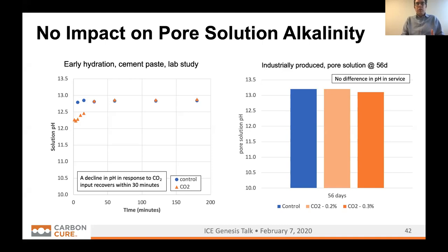Ultimately, a big question when you say CO2 plus concrete is, well, now you're carbonating the concrete. That's not a term we would use. We would say it's CO2 utilization for concrete production. Concrete carbonation refers to, in general terms in the industry, we're talking about service carbonation of concrete while it's in a building or infrastructure, and it's reacting and absorbing with carbon dioxide from the atmosphere. And so what that can do over time is consume the calcium hydroxide in the concrete and reduce the concrete pore solution pH. And if the pore solution pH goes down far enough, you can cause the ferrous reinforcement inside to start to corrode. And so this can be a durability issue.